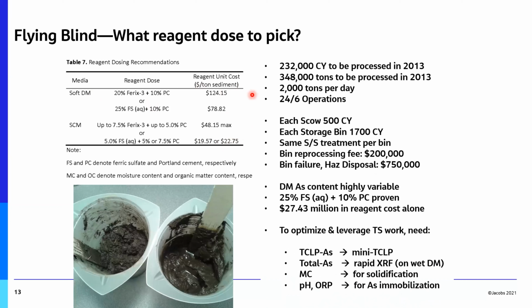And so when you run the numbers on that, we were going to treat 232,000 cubic yards or 348,000 tons of material in 2013 at a rate of 2,000 tons per day. So that was about 4 to 5 scows, 24/6 operations. Each scow is 500 cubic yards, and it can be highly variable in terms of what's in that scow. Each storage bin was 1,700 cubic yards. If you failed a bin based on 3 TCLP tests on that bin, or that 1,700 cubic yards, to empty out that bin, retreat it, and put it back in the bin was $200K. If you then failed a second time, you had to go to hazardous waste disposal at $750,000 for that 1,700 cubic yards. So significant penalties here if you did not get your dosing right and immobilize arsenic the first time.